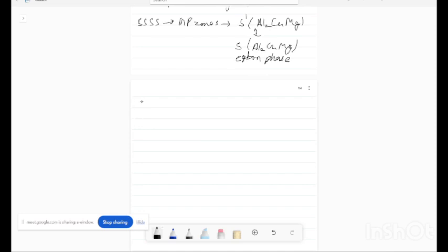In the second alloy, Al 2124, in the 2124 alloy, iron and silicon are minimized to a lower level to maintain the fracture toughness of the alloy.